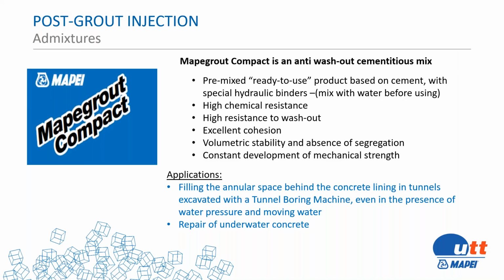Next slide. We also have admixtures in the UTT lineup. Mapegrout Compact is an anti-washout. One of the reasons why I'm showing this material here today, even though we have plasticizers and superplasticizers, is we actually use this quite a bit when we have the influx of groundwater. Groundwater is the most difficult problem during excavation work underground, because the water increases the pore water pressure and decreases the shear strength. So by adding an anti-washout, it increases the cohesion. When you add the anti-washout, it prevents the washout of the fines in the cement. Where the admixture is used, the water cement ratio becomes basically the water binder ratio. So we're very lucky to have these materials.